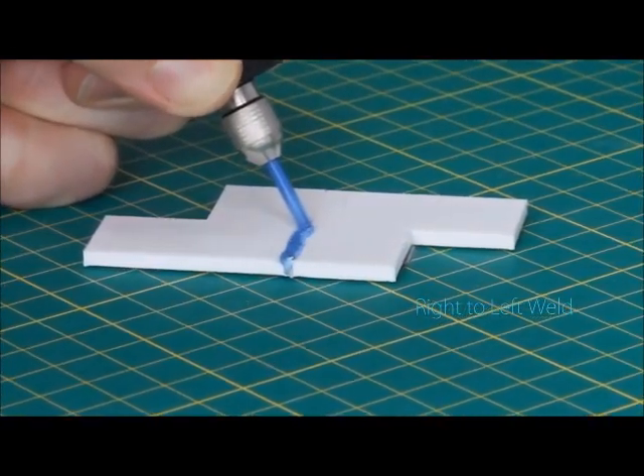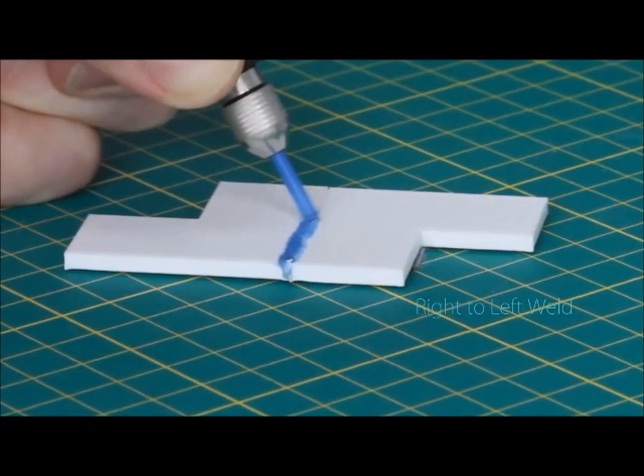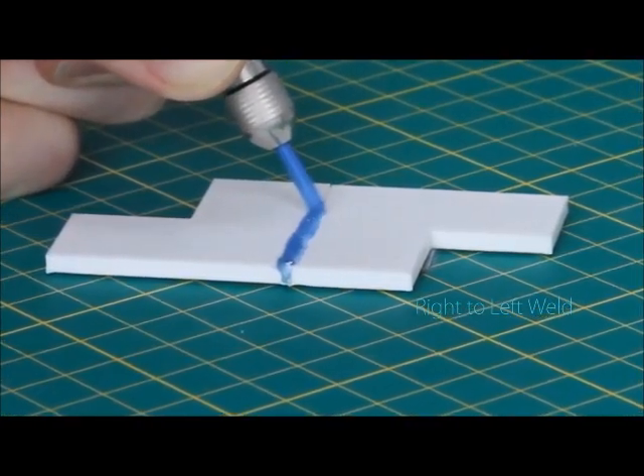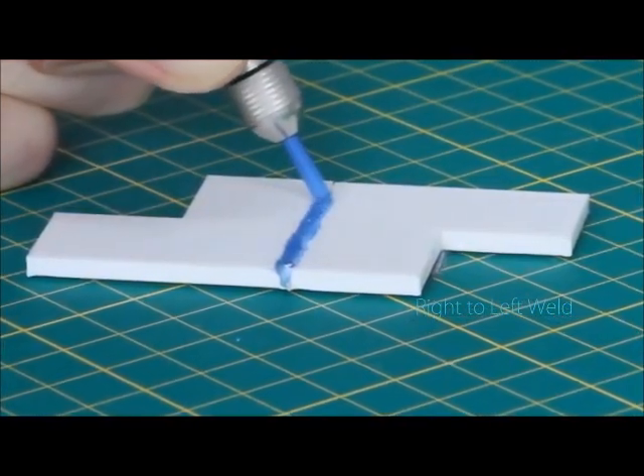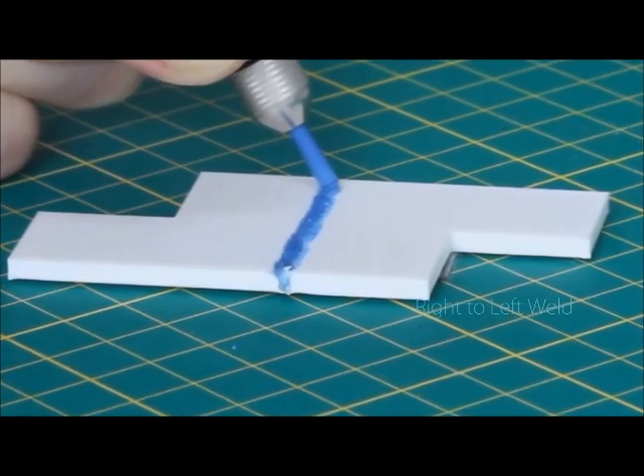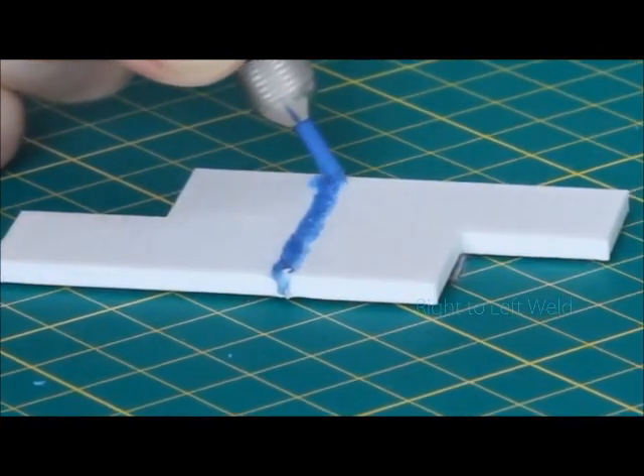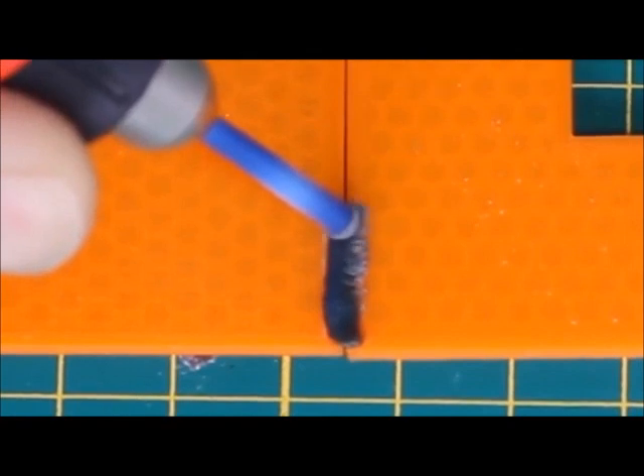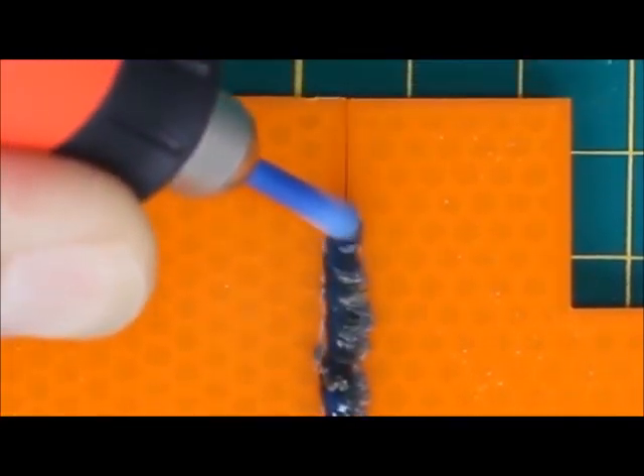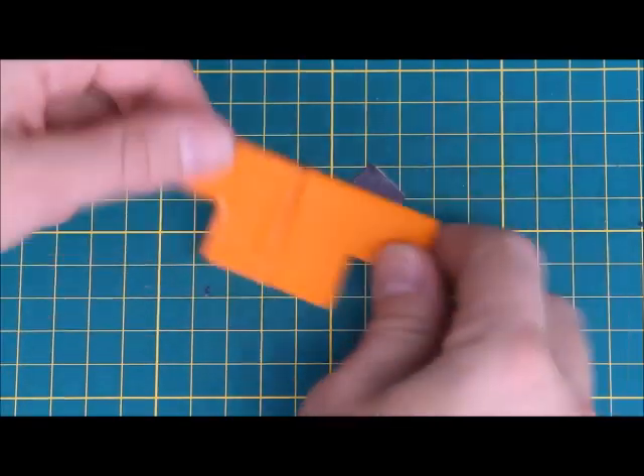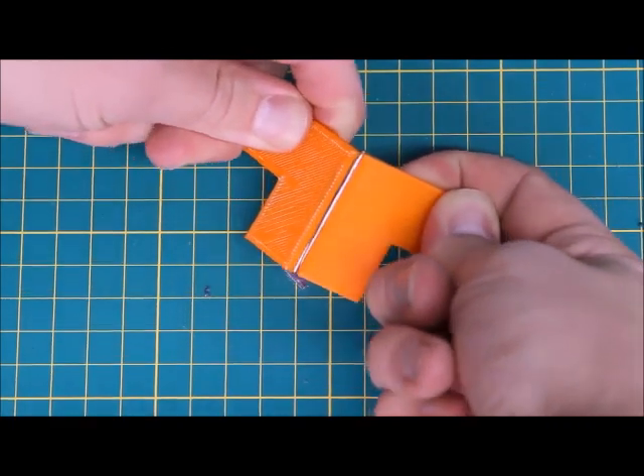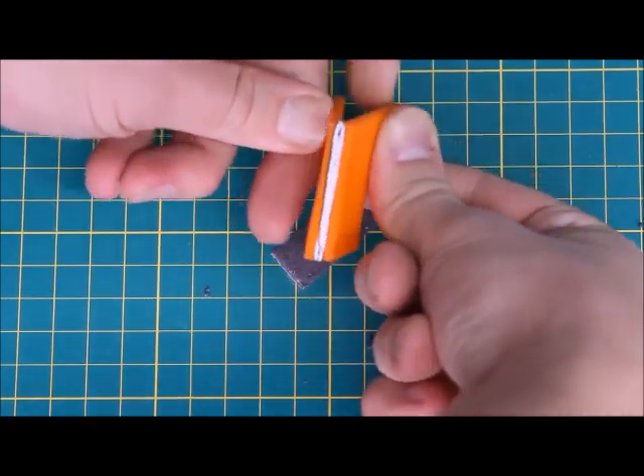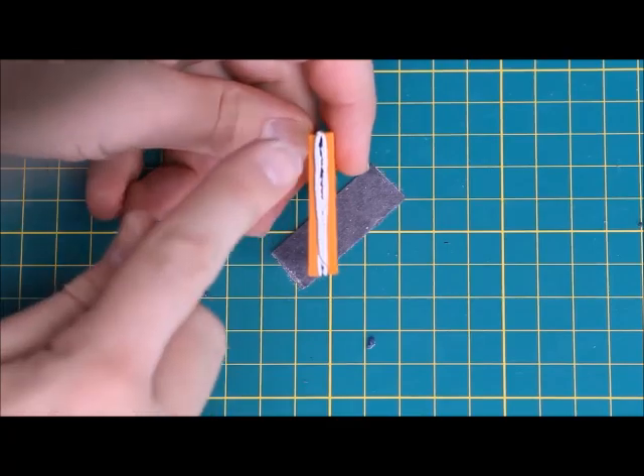With this method, you still cut a channel for the weld to sit in, and because the plastic is dragged and deposited on the right hand side, it builds up on top of the seam line. At the right speed and pressure, this is a very effective welding method. When broken apart, you can see how the right to left weld has good penetration, and the weld also sits proud of the surface, which is ideal if you want to grind it back to a flat.